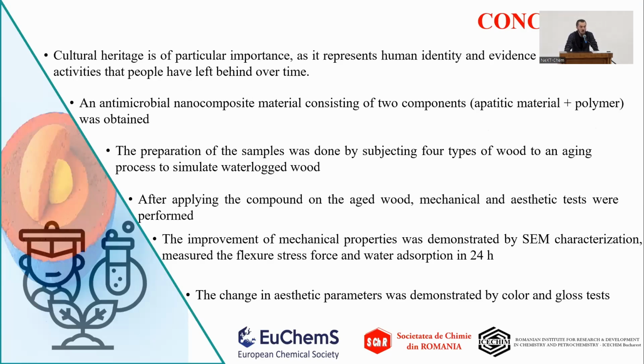To conclude the study, we can say that the cultural heritage is of particular importance as it represents human identity and evidence of activity that people have left behind over time. An antimicrobial nanocomposite material consisting of 2 compounds was obtained. The preparation of the sample was done by subjecting 4 types of wood to an aging process to simulate waterlogged wood. After applying the compound on the aged wood, mechanical and aesthetical tests were performed. The improvement of mechanical properties was demonstrated by SEM characterization, measured the flexure stress force and water absorption in 24 hours, and the change in aesthetic parameters was demonstrated by color and gloss test.